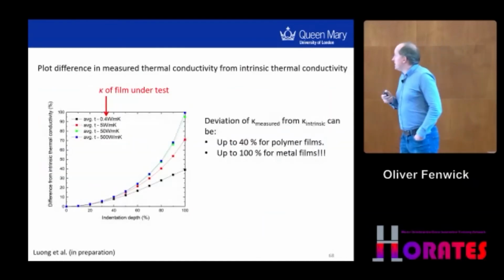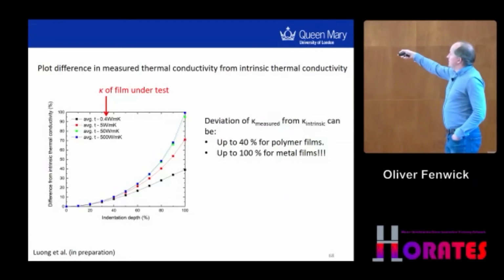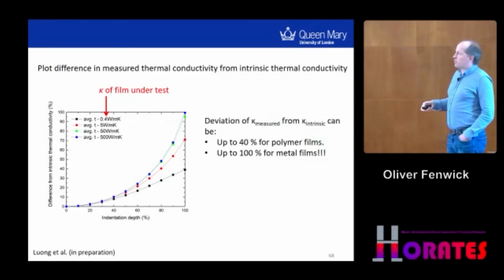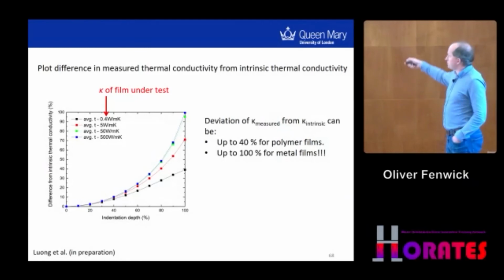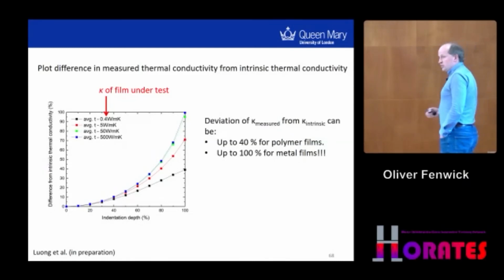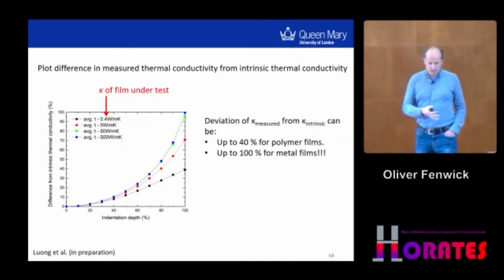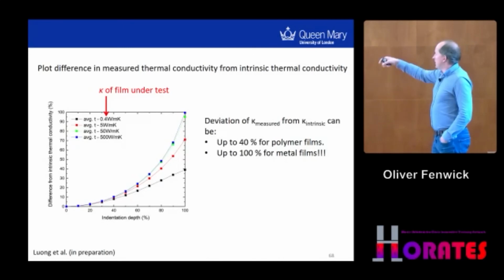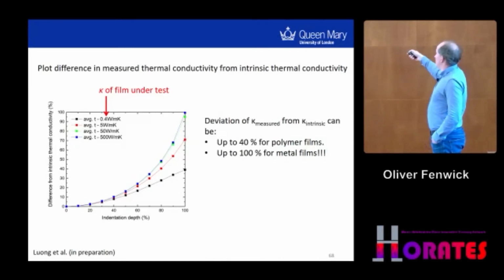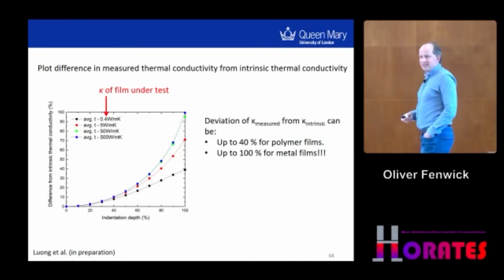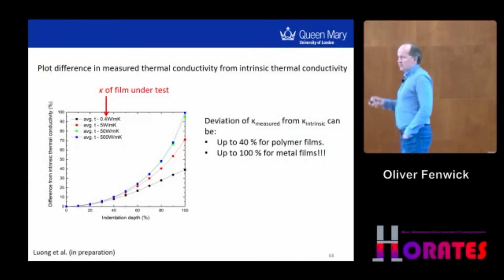What I've plotted here is the difference in our measured thermal conductivity from the intrinsic thermal conductivity of our polymer, in percent. And my student presented this to me and said, look, when we make this constriction deeper and deeper, we can get up to 40% deviation in the measured value for polymer films and up to 100% for metal films.